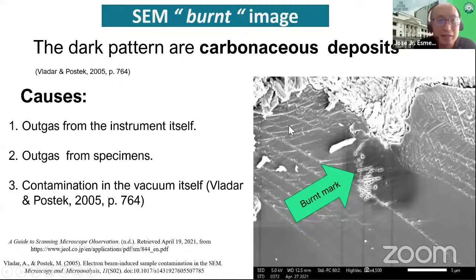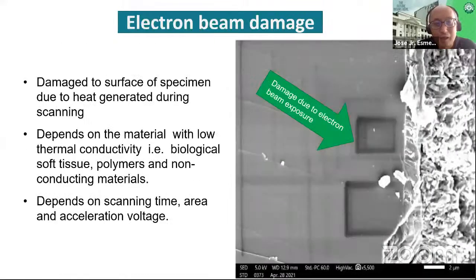Of course, one of the consequences is that some materials, especially if there are outgas or contaminants, can cause carbonaceous deposits during scanning. These carbonaceous deposits create some sort of dark pattern or burnt mark. In SEM, they commonly call it SEM burn, but actually these are carbonaceous deposits accumulating on the surface. These are caused by outgas from the specimen, or outgas from the instrument itself. That's why it's very important that samples are well prepared, in order to prevent this kind of problem.